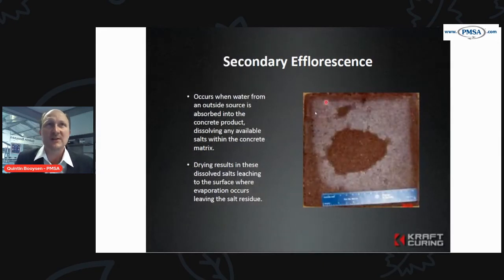So secondary efflorescence is exactly that. It occurs when the water from an outside source, so this could be a paver paved on the ground, and you have water that's not really percolating, but being drawn through the capillaries of the concrete, and it's pulling those salts to the surface, and the surface then, with the carbon dioxide, starts to form efflorescence, or calcium carbonate, like a type of limestone, almost at very micro levels, but it's on the surface of the concrete.